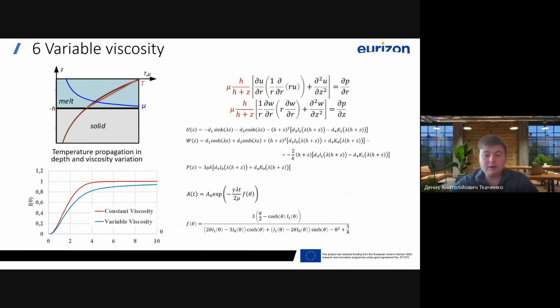The solution involves functions with modified Bessel functions, which describe radial and vertical velocities as well as pressure distribution. The time-dependent amplitude is determined similar to the constant viscosity case, but with a modified function that accounts for variable viscosity. This results in slower smoothing rates due to the high average viscosity. The difference between the variable and constant viscosity functions is shown, demonstrating the reduced smoothing rate. The same solution applies to periodic inequalities with adjusted parameters for the specific geometry.